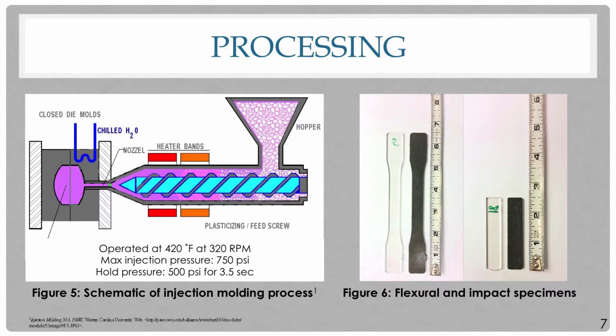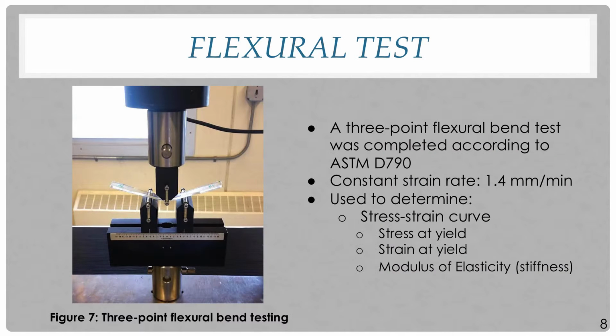This process was run at 420 degrees Fahrenheit and at 320 RPM to produce our flexural and impact specimens. Using the flexural specimens from the injection molding process, we ran a 3-point flexural bend test following the ASTM D790 standards set by the American Society for Testing Materials. To perform this test, the flexural specimen is centered on the lower supports, and a crosshead running at a rate of 1.4 millimeters per minute exerts a force onto the center of the flexural specimen until either reaching 0.05 strain or until the flexural specimen breaks.